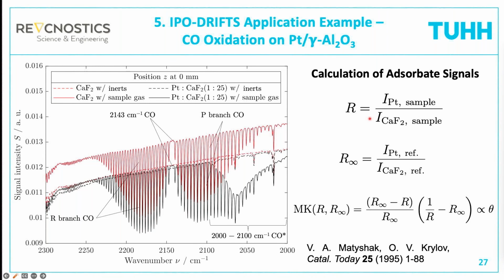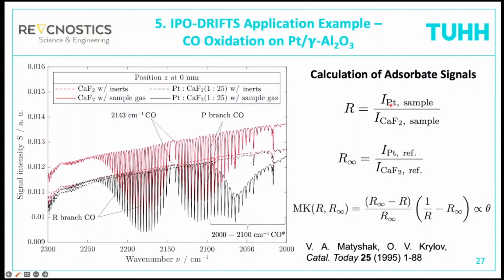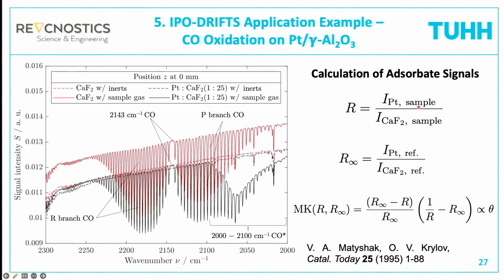Yeah. Offset and shift? I didn't show this here. These are basically the raw data. What you have to do is subtract the baseline to bring them all on the same baseline. And then we calculate the reflectivity of the catalyst in the reaction gas. This is this R value here, always with respect to the calcium fluoride. So we base the reflectivity on the reflectivity of calcium fluoride as our white standard. This gives us this R value.